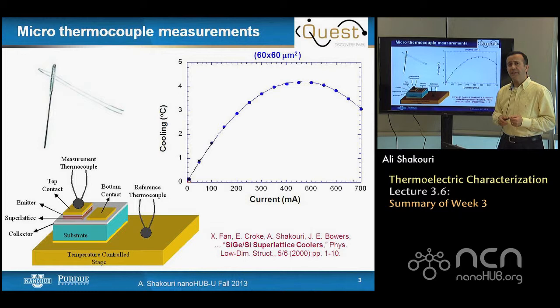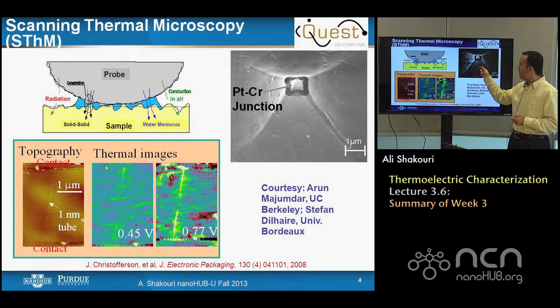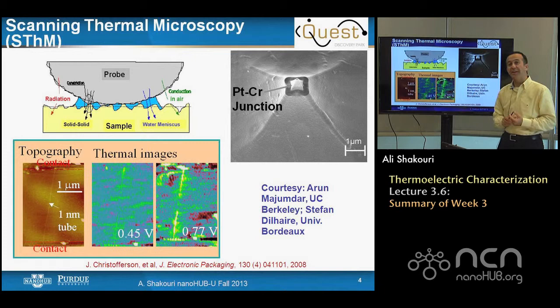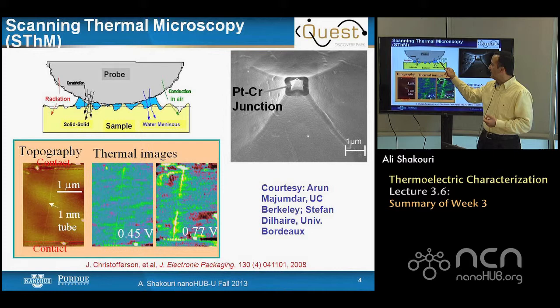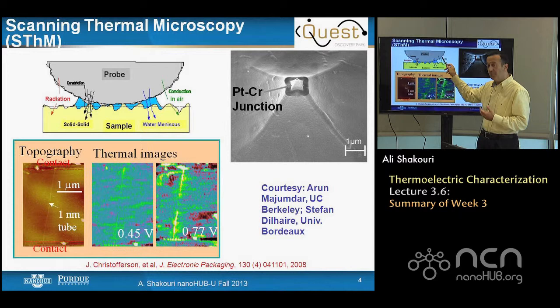In the early 1990s, the idea emerged to miniaturize this for the nanoscale — fabricating the thermocouple junction at the tip of an atomic force microscope. That's the principle behind scanning thermal microscopy. It works well for smooth objects like a carbon nanotube, where you can see the temperature profile of an object only one nanometer in size. But in reality, tip-sample interaction is much more complicated: it's not at one point, there is often a meniscus of water, heat conduction in the water, conduction in the air, radiation, and surface roughness artifacts. So it's hard to do this on realistic devices and samples.